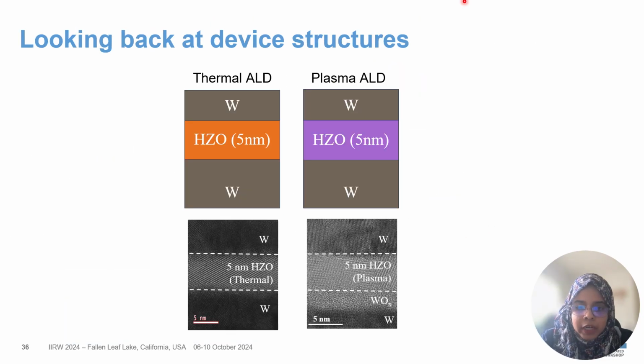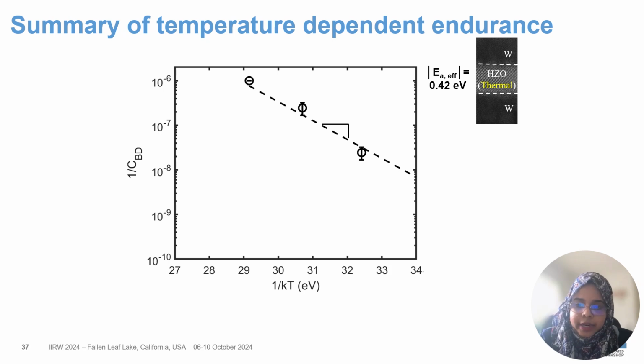Now, let me take you back to the TEM images that I was showing in the first part of my talk. You remember that we had a tungsten oxide layer at the bottom interface in the plasma ALD device. Now we wanted to decouple the effect of this tungsten oxide layer on the endurance from the effect that is coming from the plasma film itself. So for this, what we did is we intentionally grew a tungsten oxide layer in one of our devices with thermal HZO deposition. What I mean is, I will show you in the next slide.